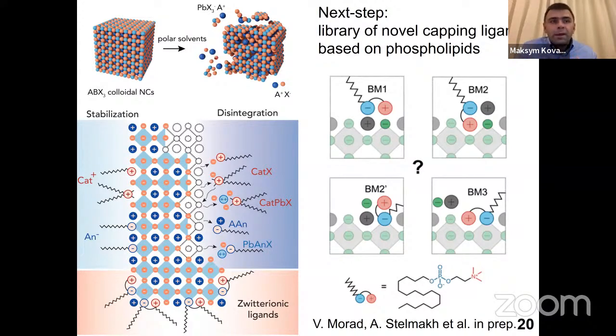And so we now undertook over the last year or so a mixed experimental/theoretical study, where we first analyzed how the zwitterion binds to the surface through molecular dynamics. And in parallel, we started to test different head groups and different tails of these phospholipids and see how that allows us to make our colloidal systems even better.